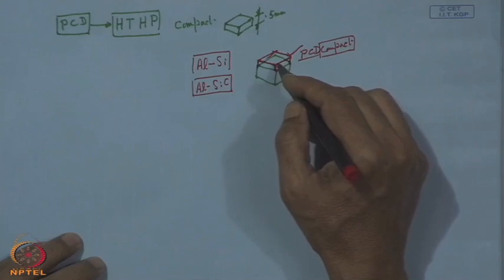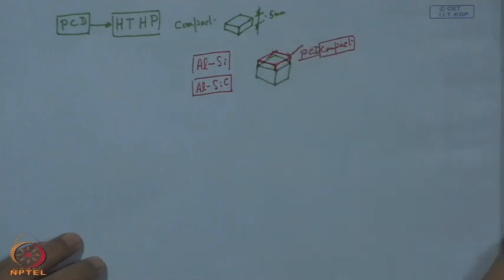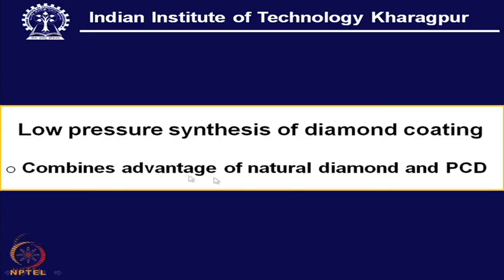So, this is a high pressure, high temperature technology, but as we see here from the very name, it is actually the low pressure synthesis of diamond. So, it combines the advantage of natural diamond, because in this case there is no need to have cobalt inside that coating. This coating can be given in the order of thickness of few micron or few tens of micron, and more importantly, it can be deposited on any substrate. What we mean, the substrate having some complex geometry. So, that is its greatest advantage, that its flexibility to match the requirement of a very complicated geometry of the cutting tool base.